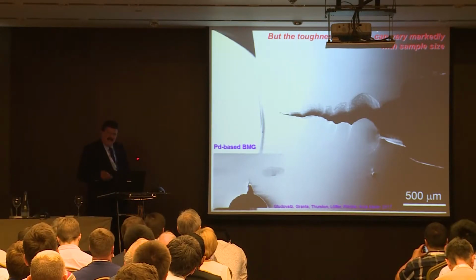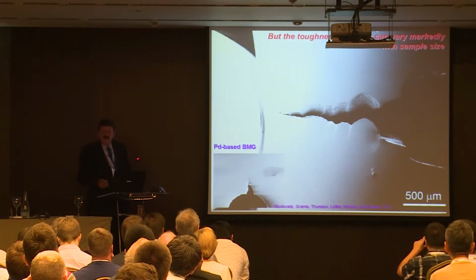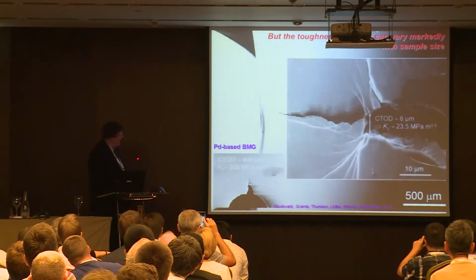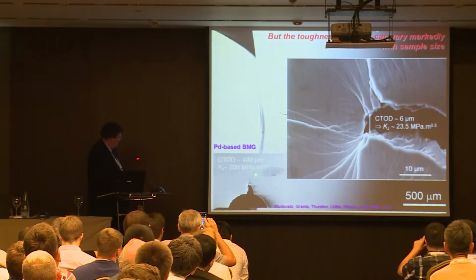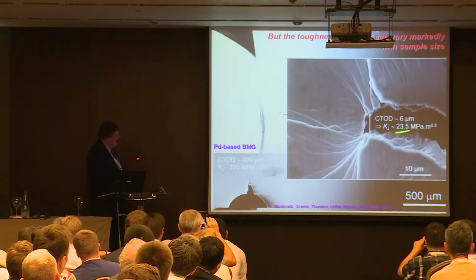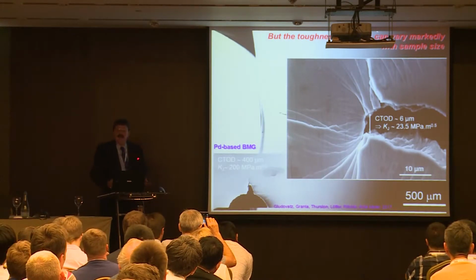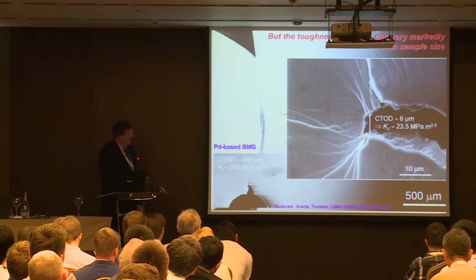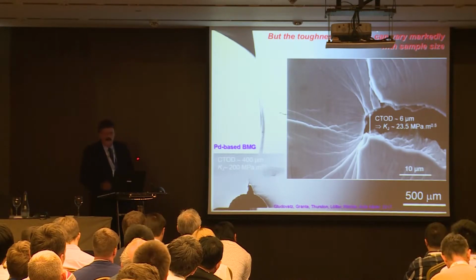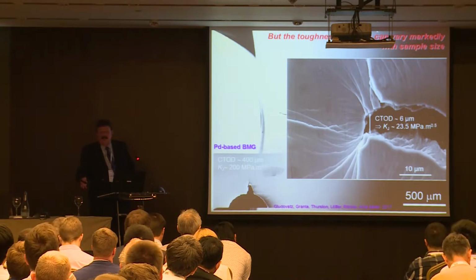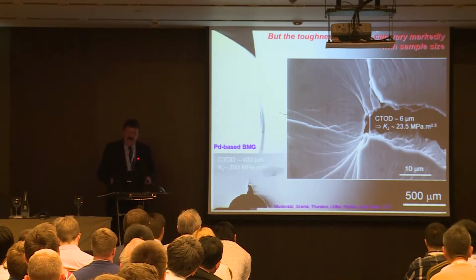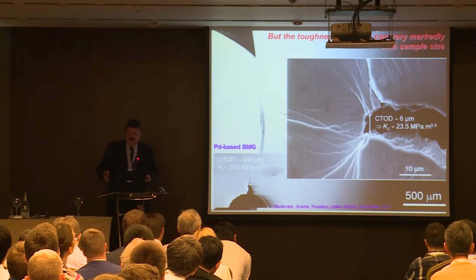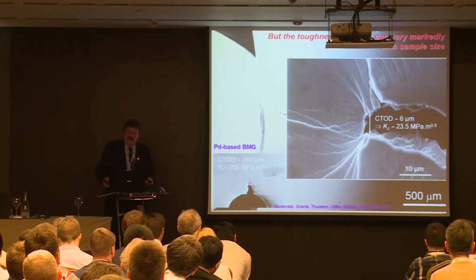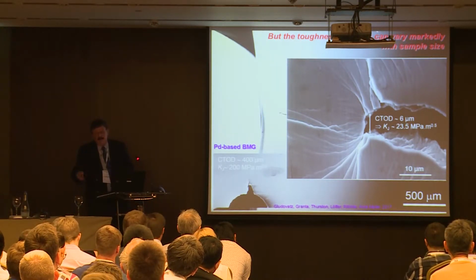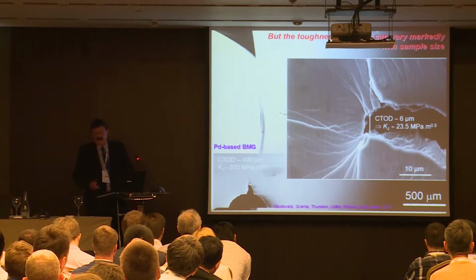So everything was good. We thought we'd conquered the world. And then we started to get more of this palladium glass. We got some from Germany. And we'd measured this very, very high toughness of 200 MPa root meters. And then we started to measure somewhat larger samples, and we started to get toughnesses that were a little different. We got down to 20 MPa root meters. So this is variability in the toughness, but it's huge variability, varying from 20 to 200 in the same material with only a small change in the size of the sample.